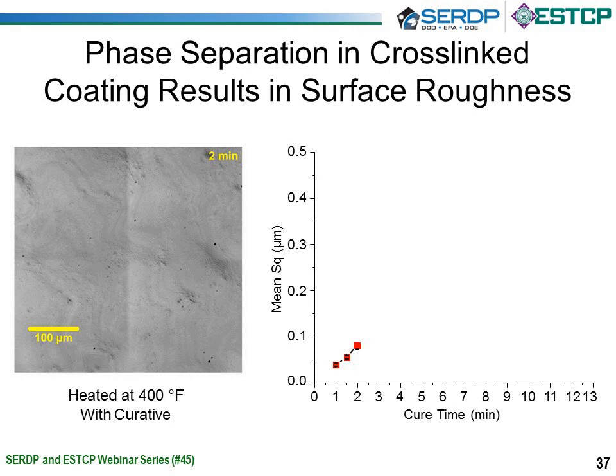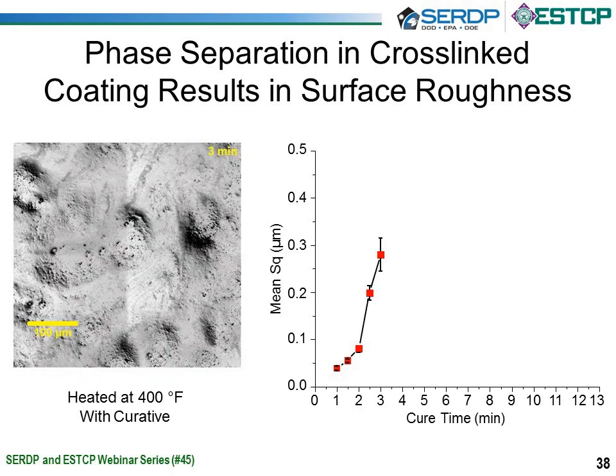There's no obvious sign of domain formation in the image as shown, and we believe that at this point it's still a melt flow process given the even coating of the surface. Likewise, we believe that the deblocking of the protected isocyanate is just starting to occur. On slide 38, at 3 minutes, we see a rapid increase in surface roughness, both in the image shown on the left as well as the root mean square analysis graph on the right. Domain formation is starting. It increased the surface roughness, and this correlates to what will ultimately result in gloss lowering effects through the surface texture.